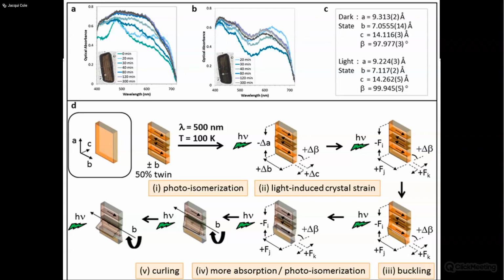In terms of the crystal lattice, the beta value is quite significant in its change between dark and light state. So from sort of 97.9 to 99.9, that's quite a big change. And again, we tried to come up with a mechanism to explain what was going on. The crystal, by the way, is actually a 50% pseudomerohedral twin, and that's probably quite important in terms of the mechanism.